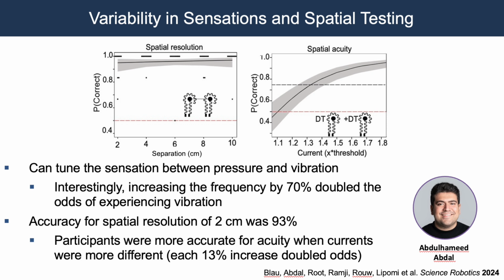The other thing that we're able to do with this technique is enhance the contrast in 2-point discrimination tasks. So if you have control over the parameters of 2 adjacent electrodes and you apply different signals to adjacent electrodes, you can actually increase the resolution, or decrease the distance at which it's possible to distinguish 2 different stimuli occurring simultaneously. It's like having 2 needles that press into the skin. You're actually able to get those needles closer if the 2 stimuli are more and more different. So that contrast improves the resolution.